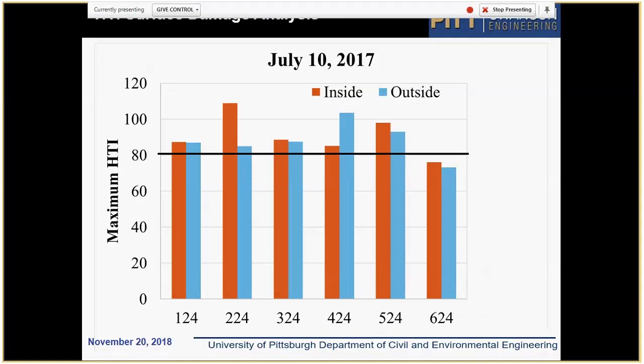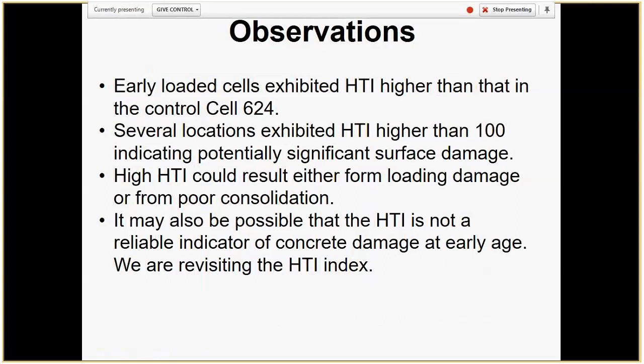So we are still working on revising this index, and the reason why we're not confident this time is that when we review the data more carefully, we found that the analysis we applied may not be adequate for the cases when velocity is much lower than for mature concrete. The index was developed for velocities of about 2.6 kilometers per second, 2.8 kilometers per second. Now we have 2.4, and that might have an effect, so we might need to adjust it. So basically, at this stage we can't rule out that there is damage, but we don't have any definite answers if it's there or not.